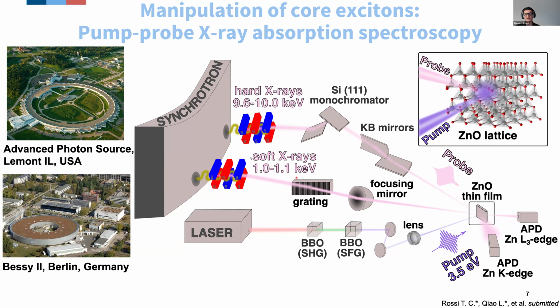And at this energy, we are resonant with the zinc L3 edge. The X-rays are monochromatized, focused, and this time the measurement is performed in transmission of the zinc oxide thin film. That's much more convenient to do in the soft X-ray range.